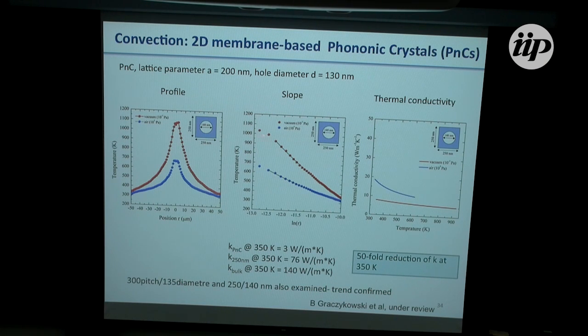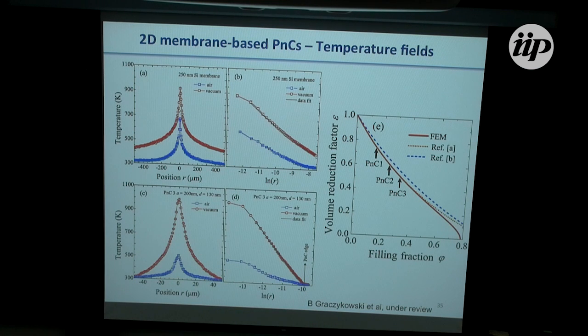The slopes for vacuum and air are shown here, and the steeper slope in vacuum corresponds to a lower thermal conductivity, as shown here. So we were able to measure the thermal conductivity up to about 900 Kelvin. I think the message is that we observed a 50-fold reduction in the thermal conductivity at 350 Kelvin. And a similar trend was observed for the other period. The temperature fields, now with respect to the filling fraction and the volume, are here. So you can compare here the 250 membrane, temperature in air and in vacuum.